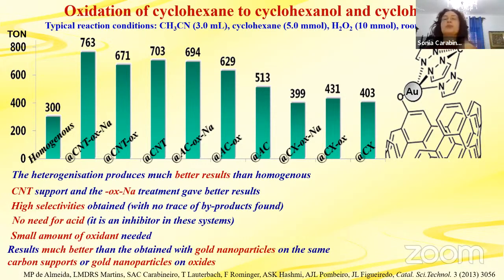And the results of the gold scorpionates anchored on carbon materials were much better than those obtained with gold nanoparticles on the carbon supports and gold nanoparticles on oxide supports.